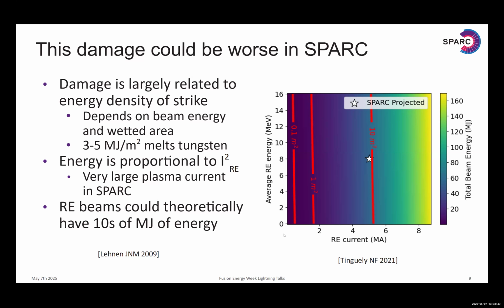And so what I've done here is I've scoped what potential runaway electron impacts could look like. I've scoped from 0 to 8.7 megaamps of runaway electron current, and I've also scoped what the average energy could look like. And then on the graph, I've put the wetted area for which the beam exceeds that melt threshold. So if you look at this simulated SPARC case, which was simulated with a code called DREAM, that has about 5 megaamps of current and an average energy of about 8 MeV. You can see that this lies on the 10 meters squared contour. So that means that this simulated case could melt 10 meters squared of wall area, which is a very large section of wall. So we've got to hope that that does not happen, because that would be quite bad for SPARC operations.